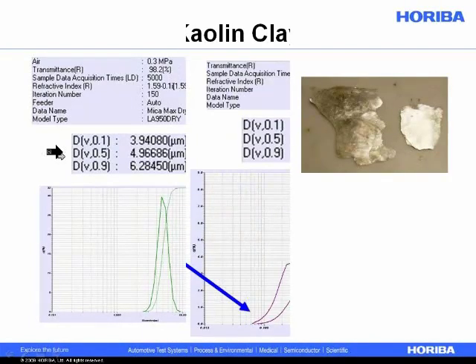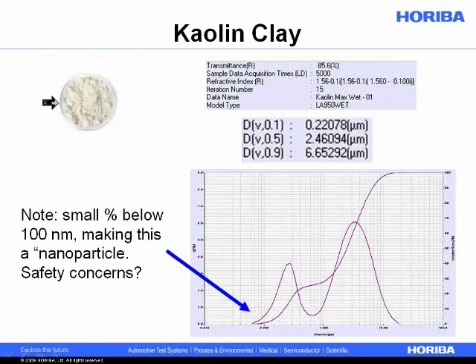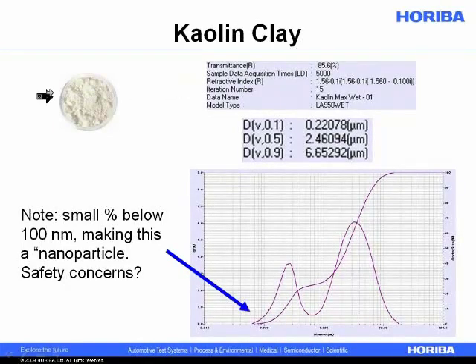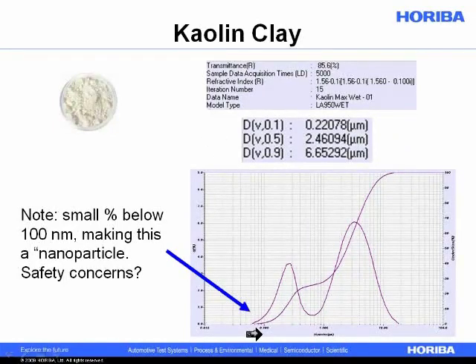I had mentioned maybe we'll add a filler to our homemade cosmetic. What we did here is use clay — kaolin clay — which most people consider the purest form of clay. We dispersed this as a wet dispersion, taking the powder and dispersing it using a surfactant. When we measured this using the LA-950, we see two peaks — a larger and a smaller — with a D50 at two and a half microns. The point at 0.1 microns represents 100 nanometers.